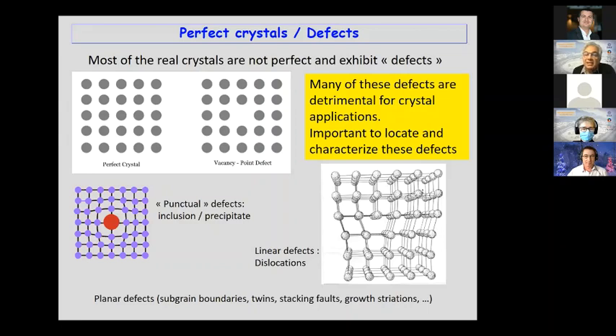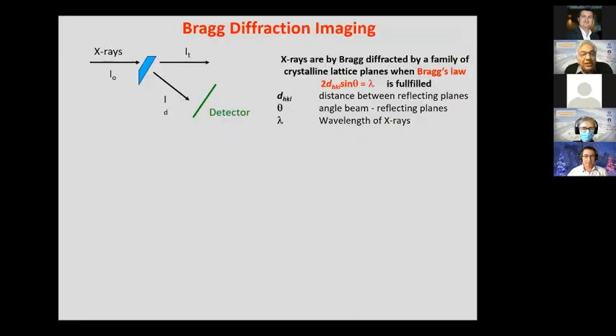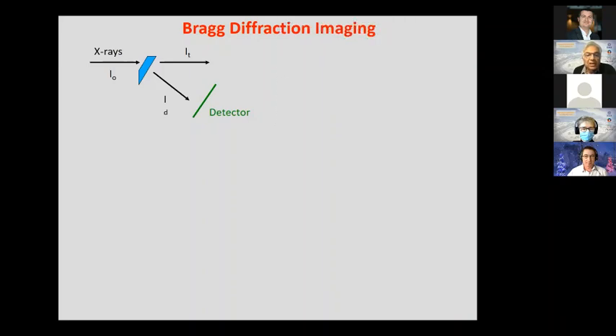Many of these defects are detrimental for crystal applications, and so it's very important to locate and characterize them. Bragg diffraction imaging is a very good technique to characterize these defects. It's based on X-ray diffraction by crystals, and X-rays are Bragg diffracted by a family of crystalline lattice planes when Bragg's law, 2d sin theta equals lambda, is fulfilled, where d is the distance between reflecting planes, theta is the angle between the beam and the reflecting planes, and lambda is the wavelength of the X-rays.